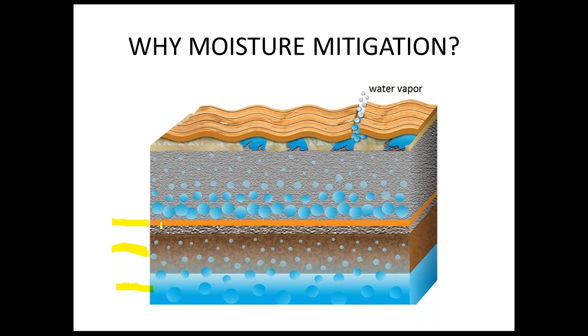That vapor barrier will only cut off portions of vapor — the perm rates are very low and it really doesn't prevent vapor from entering the slab. Water vapor molecules are very concentrated at the bottom, beginning to rise quickly through the slab and exiting at the top, creating problems in the floor covering: tile cupping, corners peeling back, emulsified glue turning to mush, and worse — mold and mildew. This slide gives you the understanding that moisture exists in all slabs to varying degrees and that you may have to address that situation.